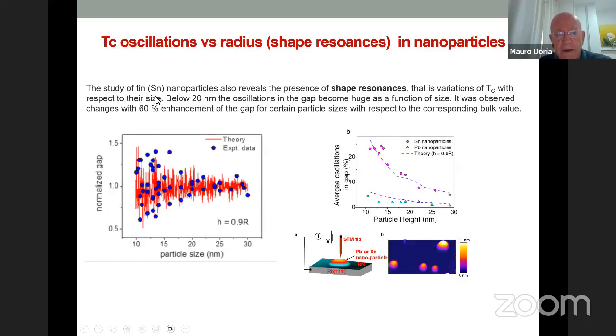For instance, one is tin nanoparticles, that you deposit on some surface. It's not a film, and you go and measure the gap in each particle, and you see that there is an oscillation in the gap according to the particle size. So again, there is a correlation between length and critical temperature, because the gap is the critical temperature in some way. So here is measured the particle height for 2 cases of lead and also for tin. And the effect is observed according to the height of the system, we are in the nanometer range.